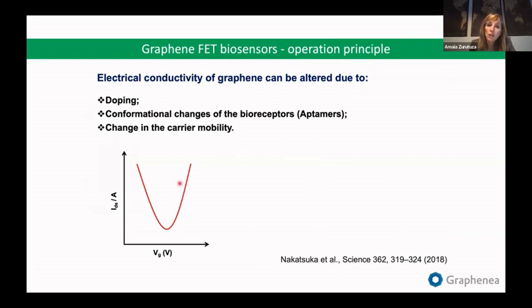If we check these transfer curves, how the source-drain current changes with the applied gate, we get this type of curve. And basically what we are following is the shift of the Dirac point, or charge neutrality point, when you expose it to a biomolecule, let's say. For example, if we put a molecule on top of graphene that donates electrons to the graphene, then it n-dopes the graphene and we see a shift to the left. If, on the contrary, we put a molecule that withdraws electrons from the graphene, then we have p-doping and we see a shift to the right. And that's the transduction mechanism of this transistor.